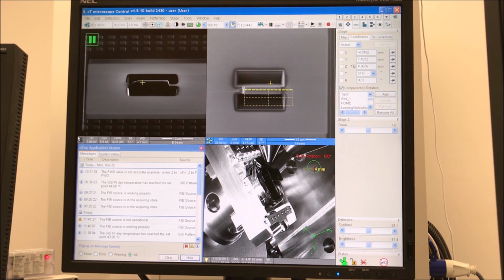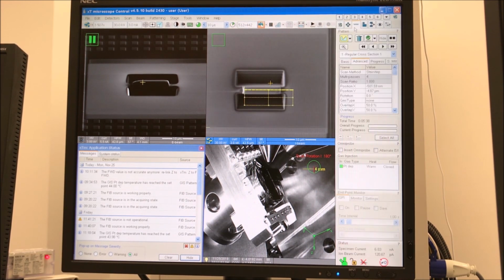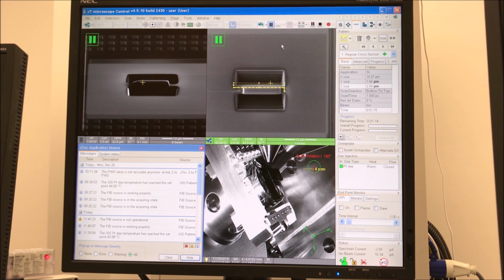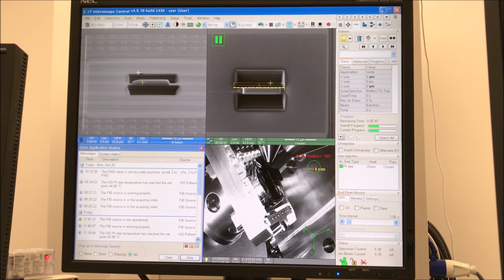I drop my ion beam current now to 3 nanoamps. And I'm going to keep the same pattern, but rotate it 180 back to the top. I'm going to change the dimensions a little to make it smaller. I reduce the Z because we're milling a sidewall and the sputtering yield goes up. So we'll go ahead and speed this section up a little bit.